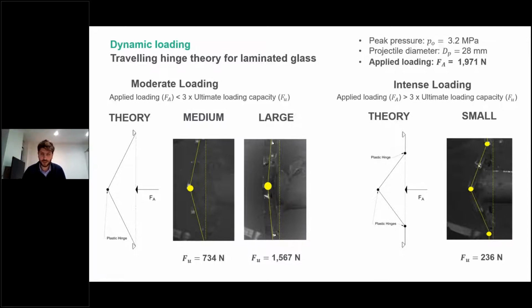On the other hand, the collapse mechanism observed for the smaller specimen is more localized, and 3 plastic hinges can be observed. This agrees with the theory of traveling plastic hinges when a short duration pulse with intense magnitude loading that is greater than 3 times the ultimate loading capacity is applied. This was actually the case for the smaller cross sections tested here when considering the recorded ultimate loading from the low temperature bending tests.